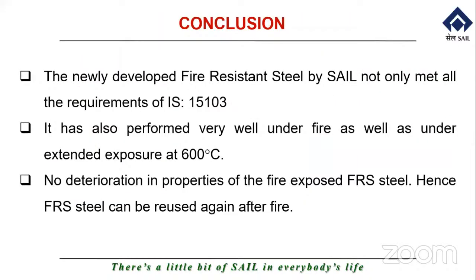So the newly developed fire resistant steel by SAIL not only met all the requirements of IS 15103, but it has also performed very well under extended temperatures, which we can see here up to 600 degrees centigrade. There is no deterioration in properties of the fire exposed FRS steel, absolutely. Hence, FRS steel can be reused again after fire.